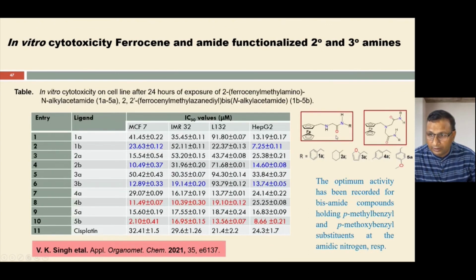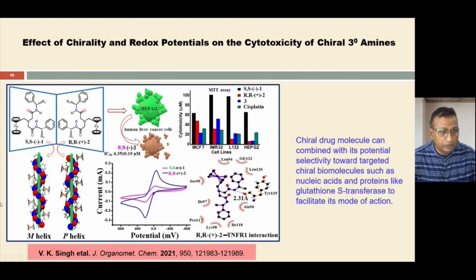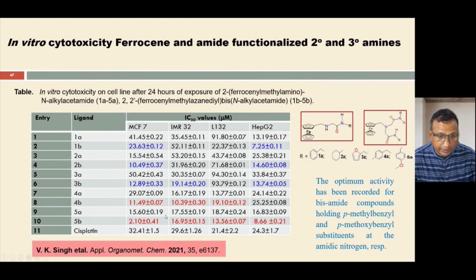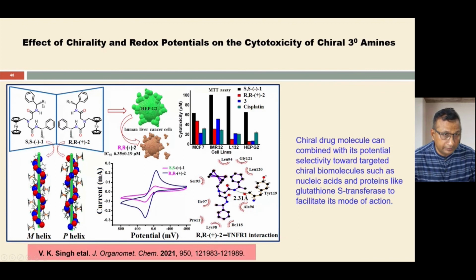After that, we thought of seeing the influence of chirality on the biological, anti-cancer activity of these amines, particularly the tertiary amines showing good activity here. So we incorporated chirality at the benzylic carbon center, and we have seen that one enantiomer with S type of chirality gives us an M type of helix, the R enantiomer gives us a P type of helix, and we have seen a huge difference in their anti-cancer activity against almost all the cell lines.